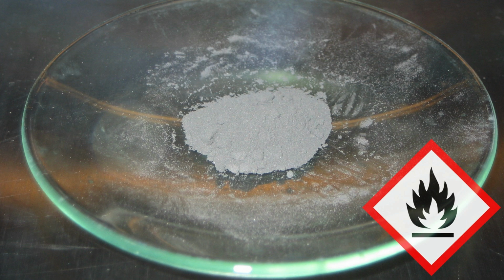During the activation process, aluminum is leached out of the NiAl3 and Ni2Al3 phases that are present in the alloy, while most of the aluminum that remains does so in the form NiAl. The removal of aluminum from some phases, but not others, is known as selective leaching. It has been shown that the NiAl phase provides the structural and thermal stability to the catalyst. As a result, the catalyst is quite resistant to decomposition, commonly known as aging.